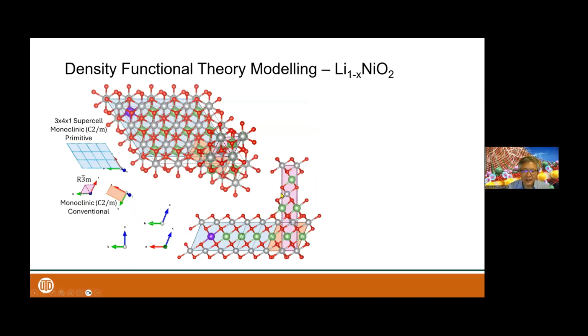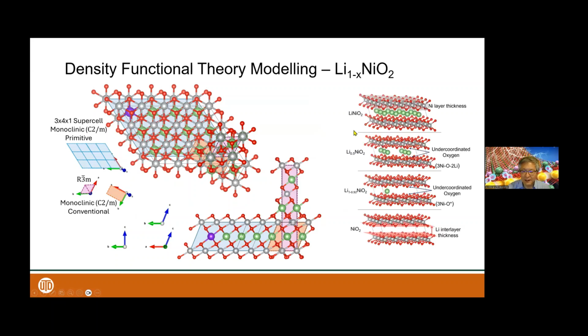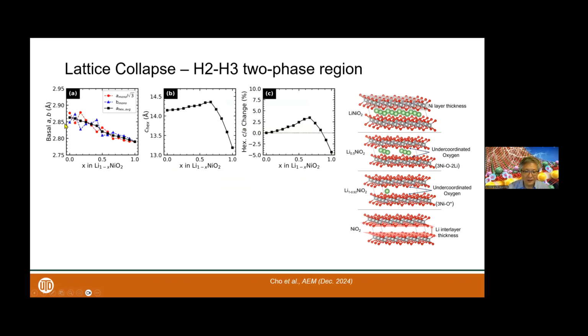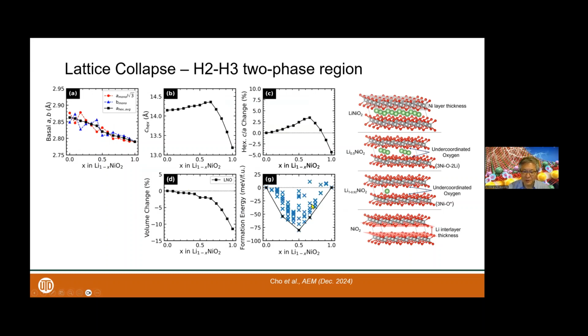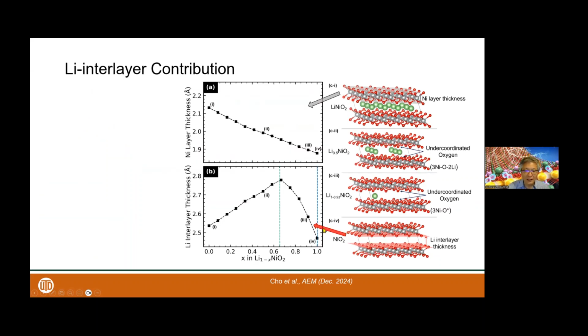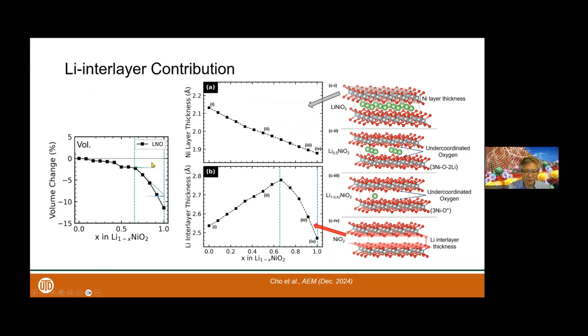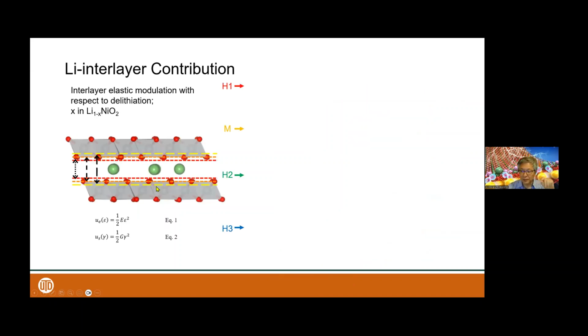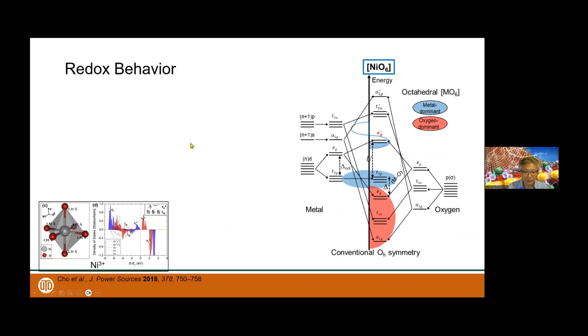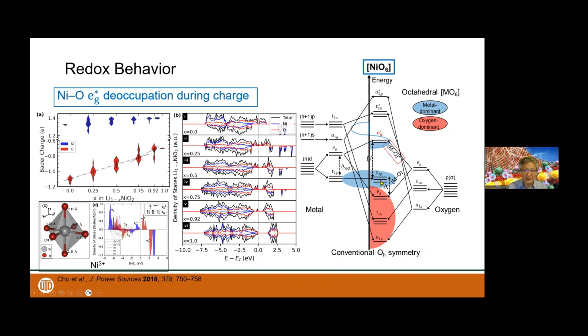So this is the kind of phase change happening, so we have done this analysis, and to do that, what's the source of the mechanical change? We have done analysis of in-plane strain and out-of-plane strain. Based on that, we looked into the phase change problem and how the volumetric change is happening between H2 and H3 phase formation. The source of this volume change is coming from this part. When you have more than 70% lithium utilization, you begin to have rapid volume change. That's the source of the mechanical pulverization and cathode degradation. So we looked into that, with mechanical property analysis and electronic structure analysis.